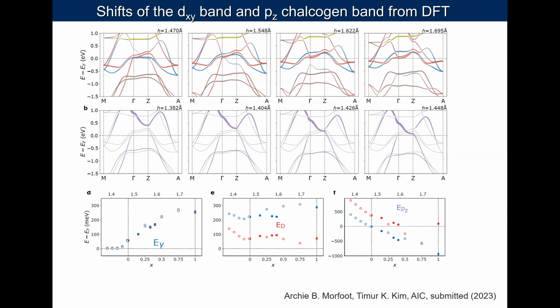And in the end, DFT gives us guidance that this band indeed will shift as we add more and more tellurium. On the second row here is what happens to the chalcogen pz band. This is the one which is important for topological effects because it will cross with the other bands at the Fermi level. So this purple band here, as we add more and more tellurium, eventually comes across at the Fermi level, and these are the conditions in which you start having surface states, which are Dirac dispersion, due to the crossing with this purple band.